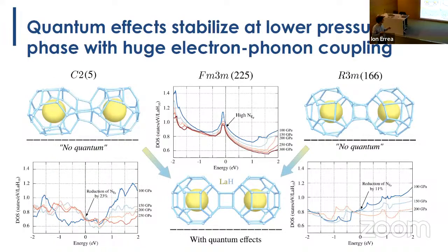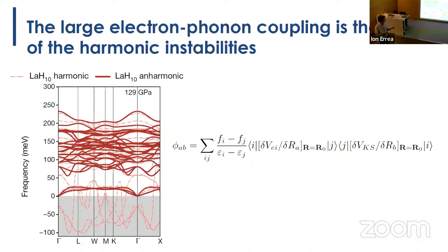Here I plot the density of states of the high symmetry phase and some of the classical structures that you find in the Born-Oppenheimer minimum for this compound. When you create a distortion, the density of states at the Fermi level is lower: here by 11%, here by 23%, depending on the distortion. So the message here is that thanks to quantum anharmonic effects, this high symmetry structure with a huge electron-phonon coupling is stable. Quantum anharmonic effects can make thermodynamically stable structures with a huge electron-phonon coupling, which, if we restrict to a classical picture of the ions, would not be stable. This is the important message.